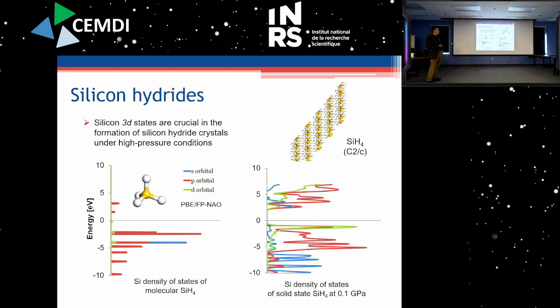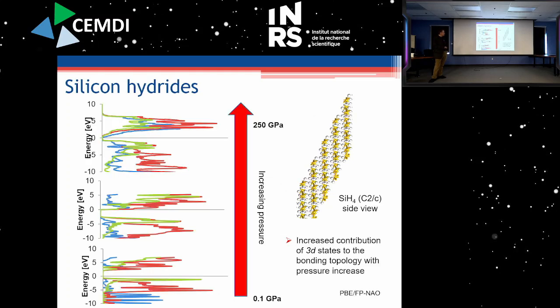But when we look at the crystalline phase of silane, so we pack up those silane molecules together under high pressure, this is the crystal structure we get. And if we look at the density of states, we see that again, for this material, under some pressure conditions, we have a significant contribution of the D states to the bonding topology of the material. Okay, and this is not necessarily obvious from that slide, but as you increase the pressure, we really find an increasing contribution. Maybe here you see a higher contribution of the d orbitals, and here an even higher contribution of the d orbitals to the bonding topology as you increase the pressure.